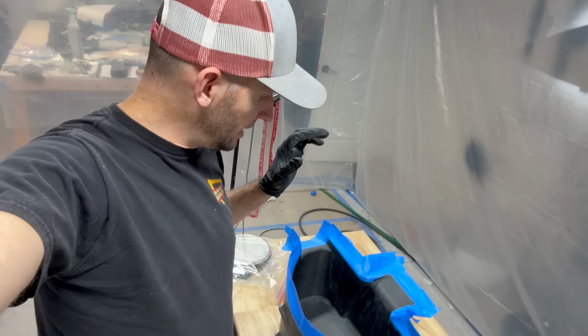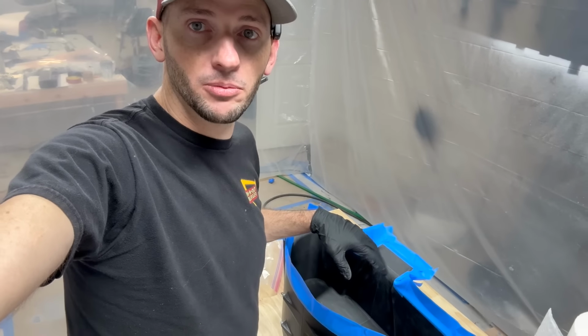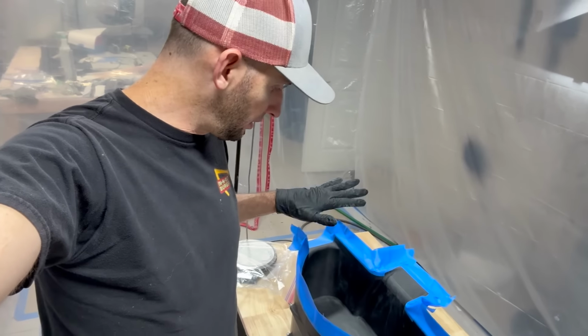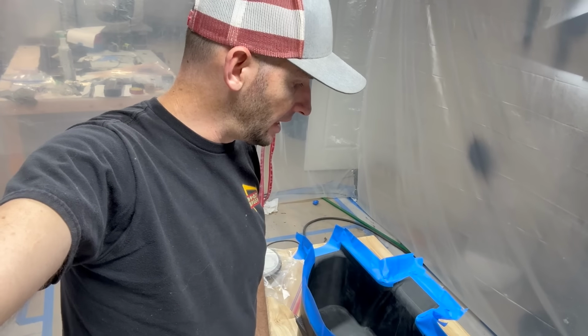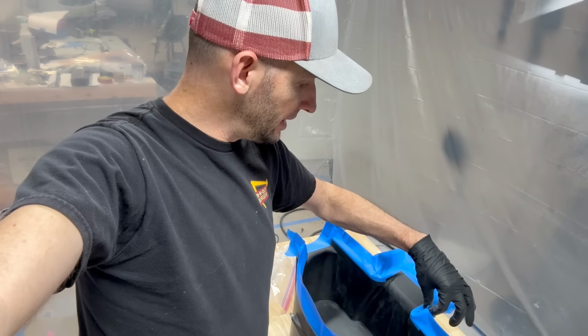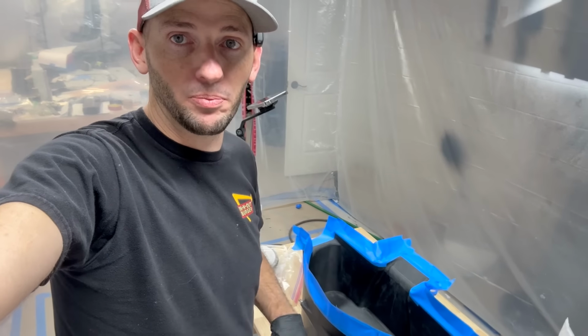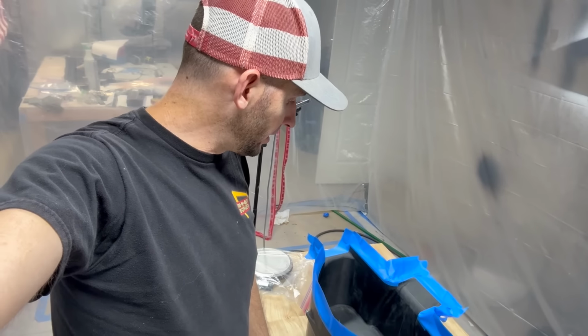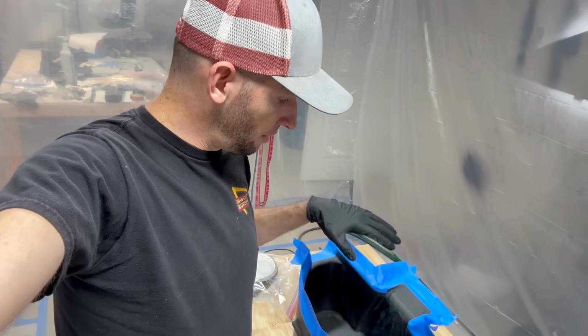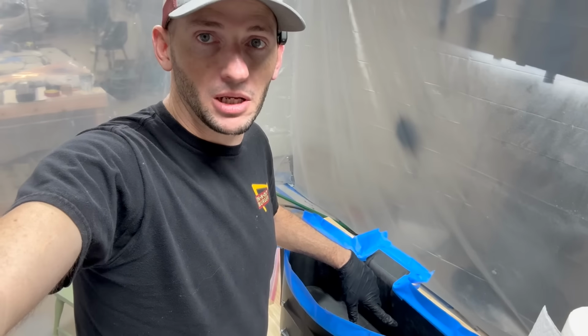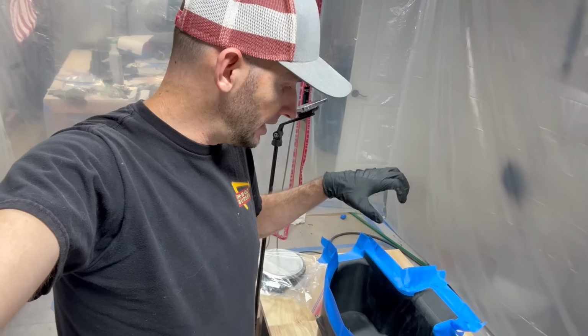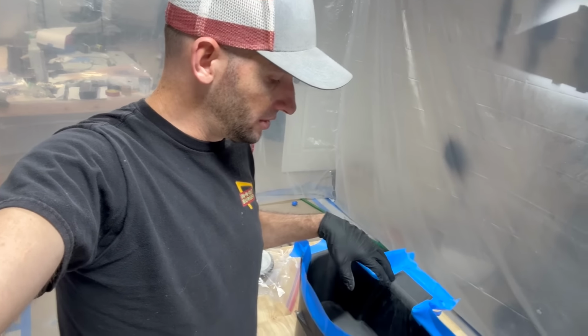I have like 5 layers of Partall Paste number 2 in here. I laid it on really thick, let it set for about 20 minutes to flash off, and then I lightly buffed it down with the goal to build material up. I wanted to fill in that rough surface finish from the 3D print and hopefully not cause too many issues with releasing the part.